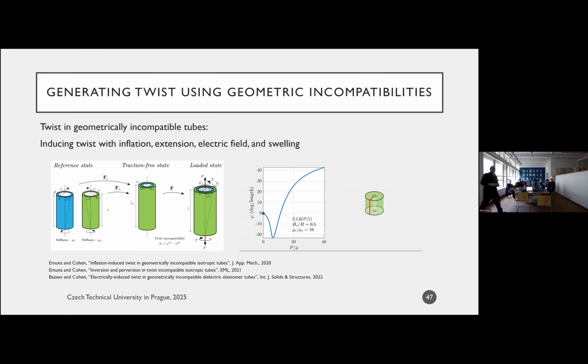Okay, so we talked a lot about twist, and this goes back to 2019, I had a postdoc and we started thinking about twist. If you look at the literature, I haven't found a lot of papers on torsion. Usually when people want to characterize materials, they do either uniaxial extension, biaxial extension, or pure shear. Not a lot of torsion out there. But the ones that do report torsion typically say, I have a structure, I apply a torque to it, and in response it twists. Or if I get twist in a different way, like in spider silk, I need to have some either chirality or an inherent anisotropy in the material.